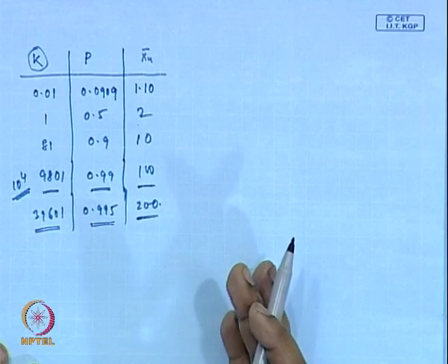Normally, typically polyesterifications are of the order of 0.1 to 10, polyamidation, which is probably the highest among the known common reactions, is about 10 to the power 2, and transesterification reactions are of the order of 1 to 10.